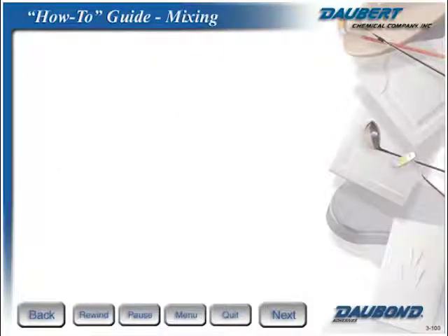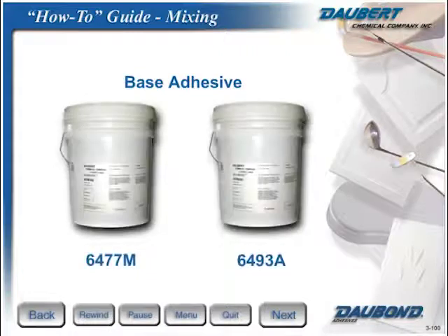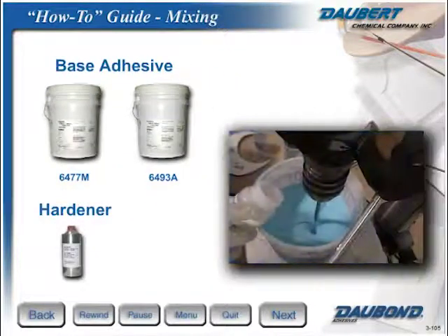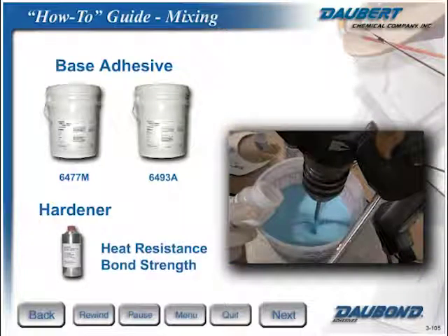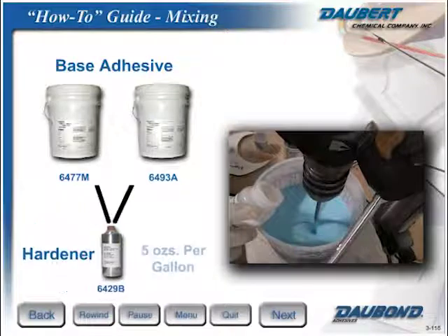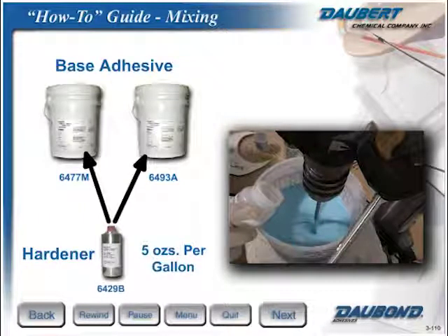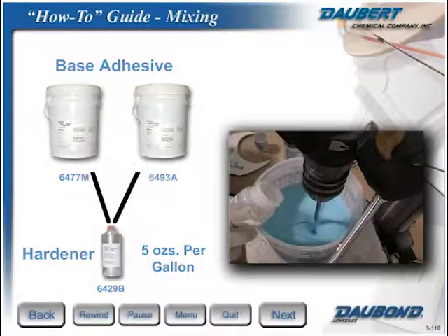Two-part systems begin with the base adhesive. Daubond produces two types, 6477M and 6493A. Part B is the hardener. You mix this into the base adhesive. This is what gives the adhesive greater heat resistance and bond strength. The hardener you'll use is product 6429B. Mix 5 ounces per gallon of the hardener to either 6477M or 6493A. The mixing amounts are the same for either base adhesive.